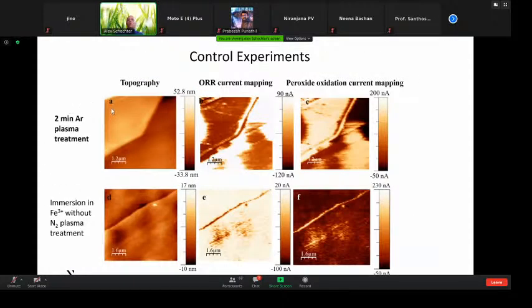One can say, well, how do you know that this is oxygen reduction? So here's an experiment using argon, and as you can see, the currents are significantly lower. And this is even more important. This is the immersion of iron without N2, before doing the N2. You can see again that we're losing all the activity.